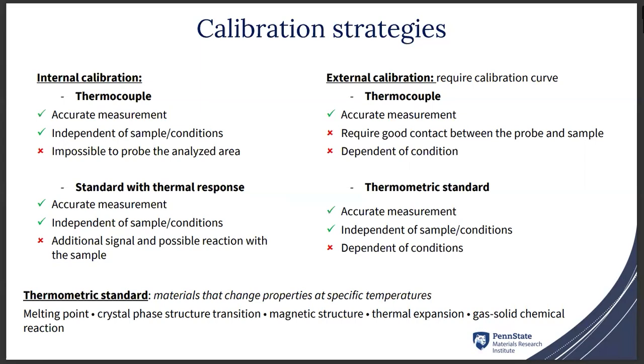The first type of internal calibration we can do is using a thermocouple where we are doing the analysis. The problem is when we are using spectroscopy, we cannot do that, otherwise we cannot analyze our sample. The second possibility is using a standard with a known thermal response, so we just add the standard to our material.